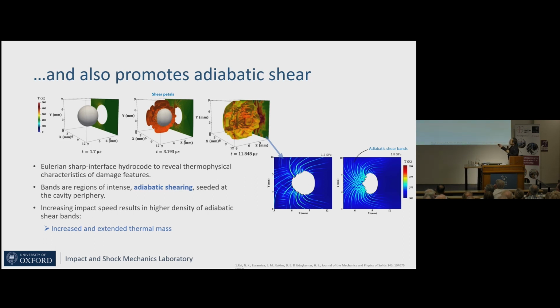That energy remains localized and it sweeps throughout the material, forming this very, very complex and some might even say beautiful crab-shaped topology of damage. If we go to higher velocity, we see that actually we start getting crisscrossing. We get a larger envelope of this thermal mass. And what we can now do is correlate the amounts of energy that we put into the system to effectively the volume of heated and activated material.